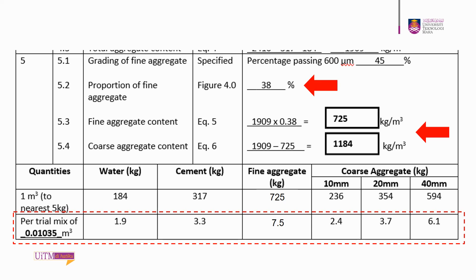Hence, the quantities per m³ for water, cement, fine aggregate, and coarse aggregate are obtained. For this example, the maximum aggregate size is 40 mm, so the ratio proportion for 10 mm, 20 mm, and 40 mm aggregate is 1:1.5:2.5 respectively. Finally, the quantities of material per m³ are multiplied by the trial mix volume to obtain the quantities of material for the trial mix.